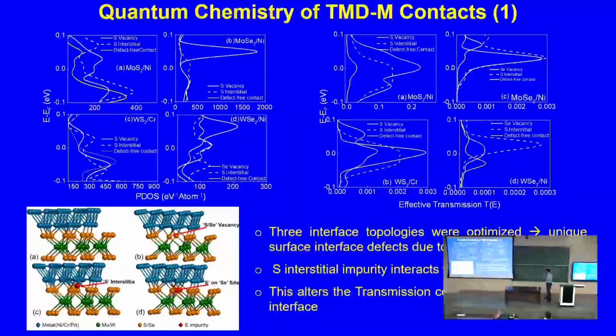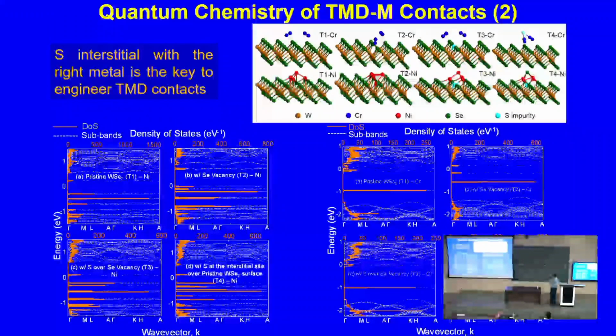Let me talk about something similar for TMDs, and then I'll come to the practical implementation. In the case of TMDs, the creation of vacancies in graphene gave us the idea: can we do something similar in TMDs? So we tried many things in TMDs. In the beginning we tried DFT. We tried sulfur vacancies, sulfur interstitials, sulfur over sulfur, selenium over sulfur, many things, and also many metal combinations along with that. To cut the long story short, under certain defect and metal combinations, we found selective donor or acceptor states. So you can create either donor states or acceptor states depending on what kind of defect you have and what kind of metal you choose.